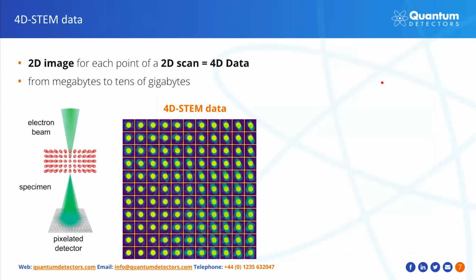Right, so now let's see what happens when we collect this kind of pattern for each point of a scan. The first thing we see is that collecting a 2D image for each probe position in a 2D scan results in a 4-dimensional dataset. This data, as I showed on the previous slide, can be very information rich, but also hungry for data storage. Compared with the standard STEM signals, which are usually tens of megabytes maximum in size, 4D STEM can quickly reach tens of gigabytes. To demonstrate how a 4D STEM dataset can be simply visualized, I have created this mosaic of two-dimensional diffraction patterns. The position of each pattern corresponds to the position of the beam on the sample.